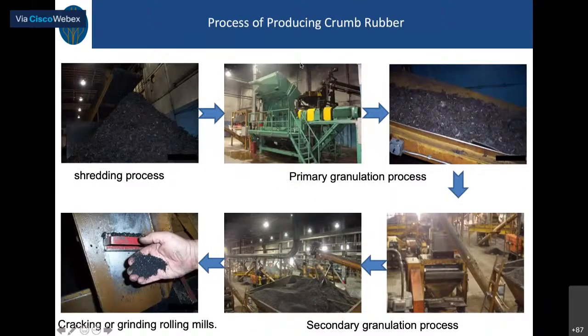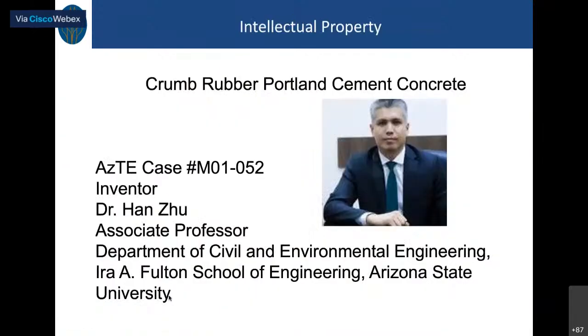The process to reduce these scrap tires to crumb rubber starts by shredding the tire, then a primary granulation process where they are reduced to chips, and then a secondary process where they are reduced to smaller chips. The last step is cracking or grinding in rolling mills, which produces the crumb rubber, and in the process there is a magnet to remove all the steel from the crumb rubber.